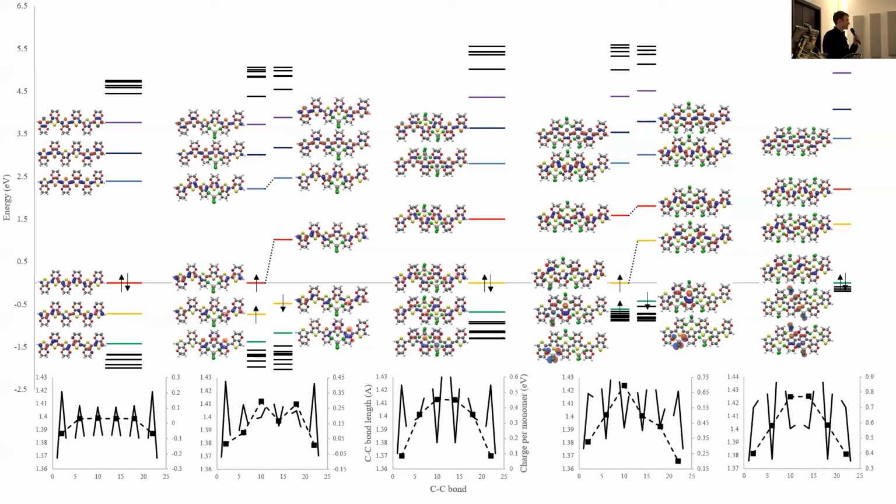And one of the fundamental things that I'm showing with my work is actually that the apparent driver for the anions to sit together is not so much driven by some force that makes it preferable for them to do that, but simply that they can't sit over the ends. So they have to force themselves together, and that's what drives these anions to sit together. And you can clearly see the Coulombic repulsion building up between the anions because it's driven up the orbitals on the anion, so they actually start featuring in the states around the gap.